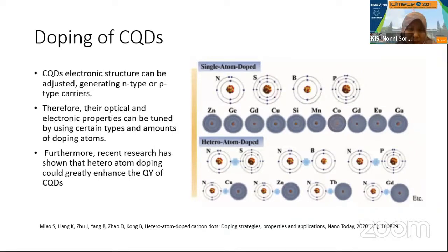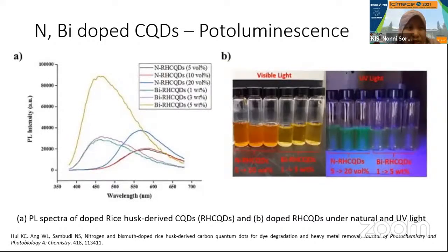And why is the doping method beneficial? It has been widely researched that the doping of the material can enhance the quantum yield of the material, right? It can also narrow the band gap, which will induce the excitation of electrons faster into the conduction band. So we hope that it can improve the performance of the material for the photocatalytic process. Okay. So we try to dope the carbon quantum dots by using nitrogen as the non-metal source and also bismuth as the metal source.